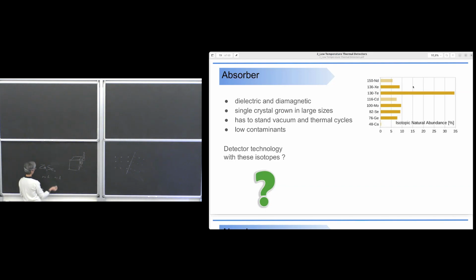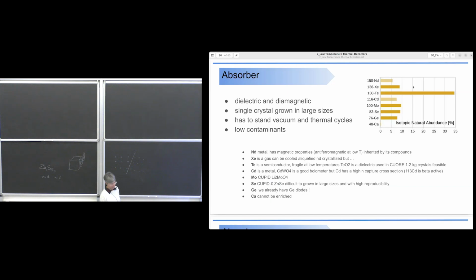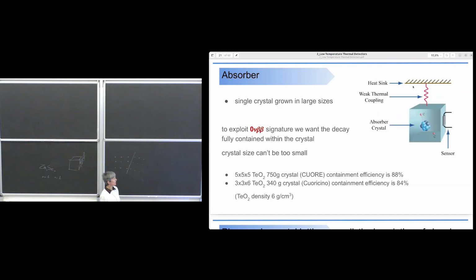But sometimes you have, I don't remember, maybe an excess of this or an excess of that. And so it's clearly visible because you have different colors of the crystals, from yellow to red. And also, it prefers to grow as a glass and not as a crystal. So there are a lot of problems. Germanium does work, but there is no reason to operate a bolometer when you have germanium diodes. And then calcium I already discussed. So this is more or less the list that I gave you.